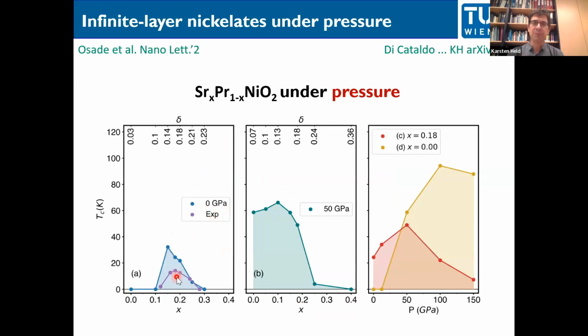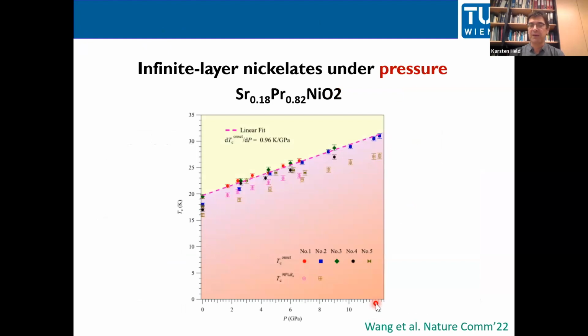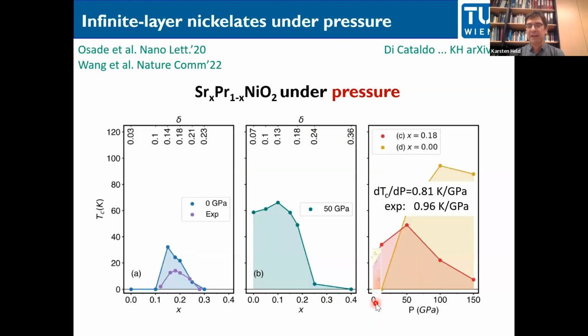Now this praseodymium nickelate, both in theory and in experiment, has a slightly smaller TC, but the agreement is again quite reasonable. What they took in experiment is the maximal TC point, that's 18% doping. 18% doping, here's a red curve, and now they apply pressure. But the pressure they applied is just 12 gigapascal. So if we squeeze that into our figure, it's only going up to here.